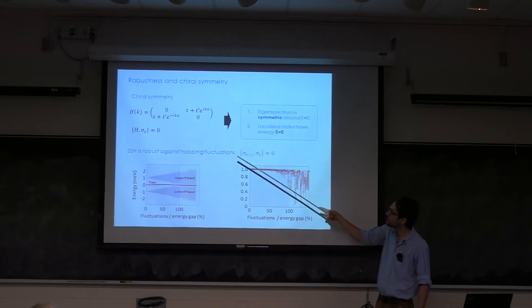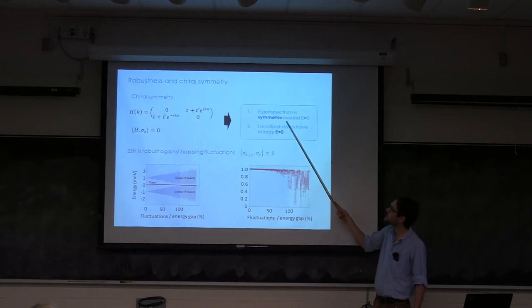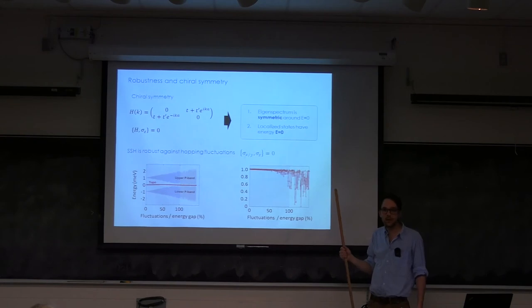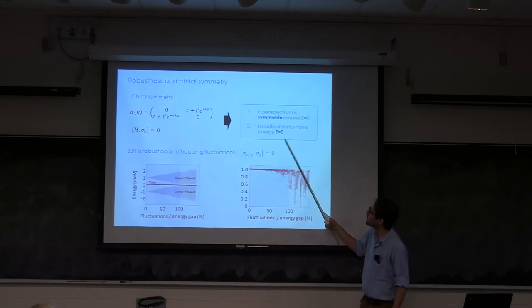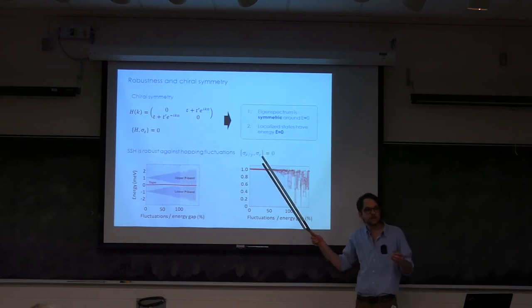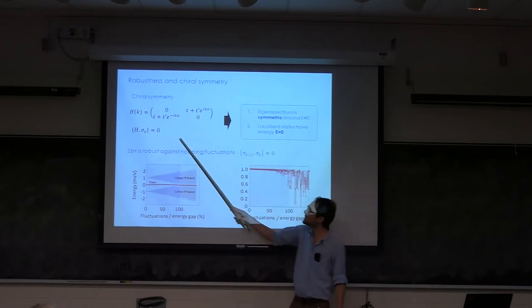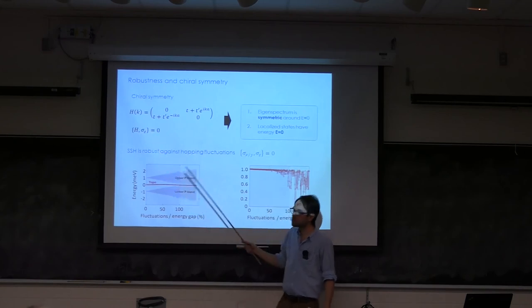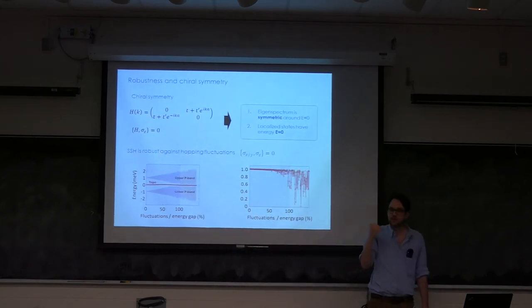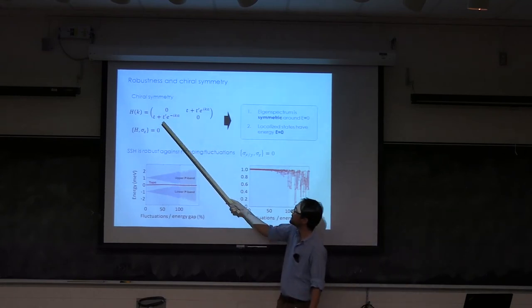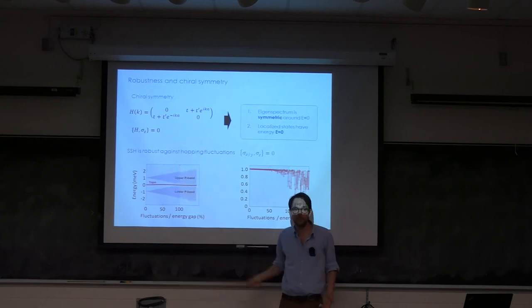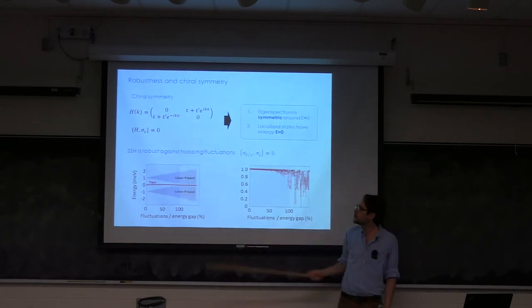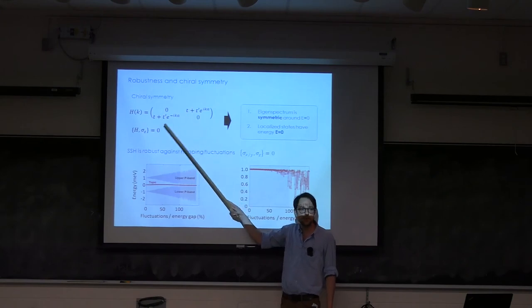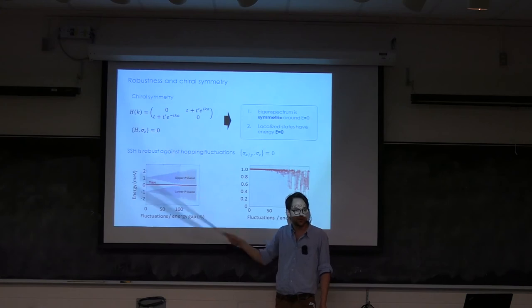First of all, if you have this, you're going to have an energy spectrum that is always symmetric around E equals zero. As well, if you have localized states, they need to be at the center of the gap. This means that as long as you preserve this, you're always going to have your edge state at the same energy, E equals zero, and that's going to be localized. And so if you start to introduce perturbation in the hopping strengths, this is one type of perturbation that you can introduce in your lattice, you don't change anything, because you're going to introduce sigma x and sigma y components to your Hamiltonian, which do anti-commute with sigma z. So you're not going to change anything.